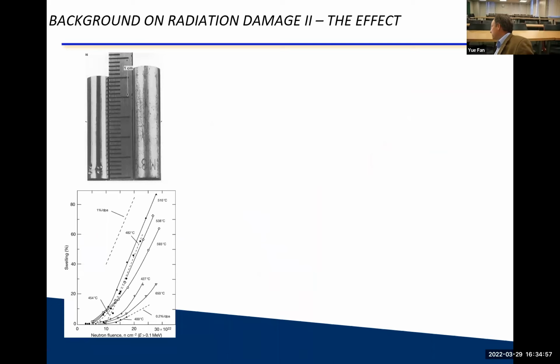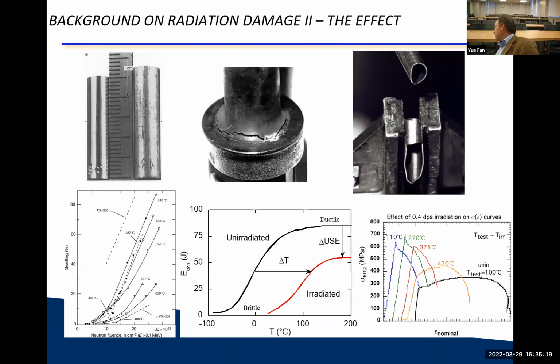Now, the result of this is that your material may swell, so you can have a volume change before radiation, after radiation, tens of percentages can happen. Of course, if you have a component, imagine a screw or a bolt that changes its length and its diameter just dramatically. That's awful. You can have cracking. Here's actually a bolt from a reactor that's caused by embrittlement. Or here's a stainless steel tube that they have just held in a vise, just to hold it in the hot cell, but then just by holding it, it actually fractured. It's that fragile sometimes. So one has to be rather careful.